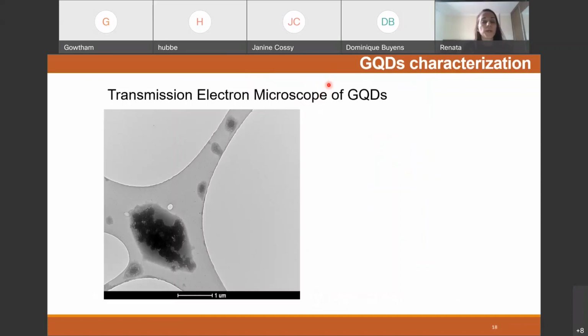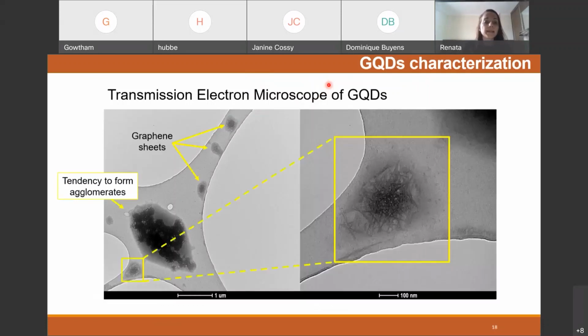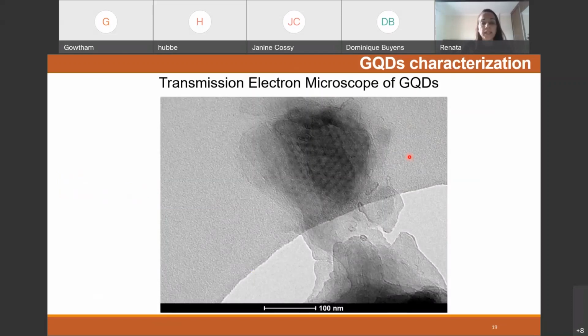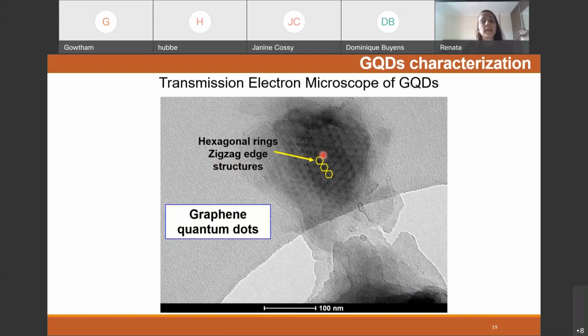The materials were analyzed by electron microscope, and it is possible to observe graphene sheets. These materials have the tendency to form agglomerates, and we highlight these graphene sheets that have this aspect. Another characteristic is the presence of hexagonal rings with zigzag edge structures. Then it can be concluded that the suspension has graphene quantum dots in our materials.